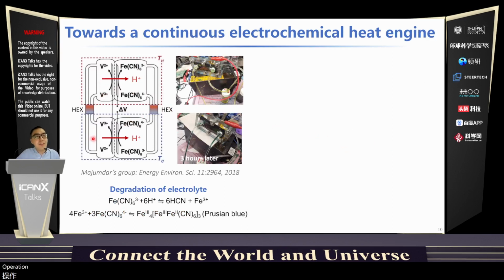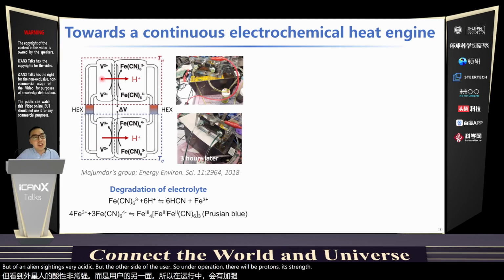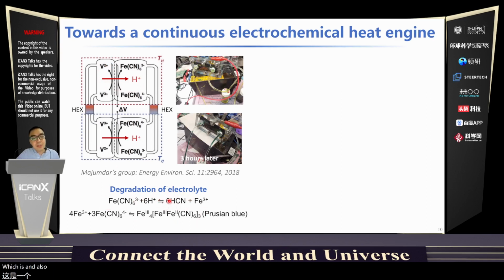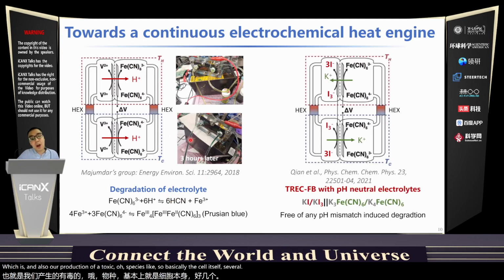In previous work, they used the vanadium electrolyte versus the ferrocyanide. But the vanadium side is very acidic, while the other side is neutral. So under operation, there will be proton exchange from the vanadium side to the ferrocyanide side. And that will induce degradation, and also production of toxic species. So basically this cell will fail in several hours.